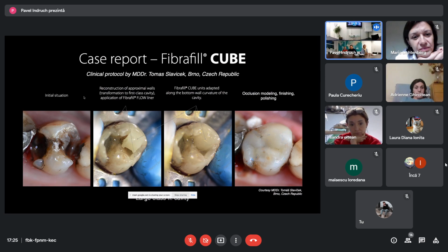This is an illustrative case where we treated an upper molar. You can see in the first picture on the left that we have to remove carious dentin or all hard tooth tissues which are degraded. In the second picture from the left, you can see the rebuilt approximal wall and one portion of Fibrafill Cube inserted in the position of the dental cusp. On the right side, the final picture shows that every portion of Fibrafill Cube is covered with conventional composite.